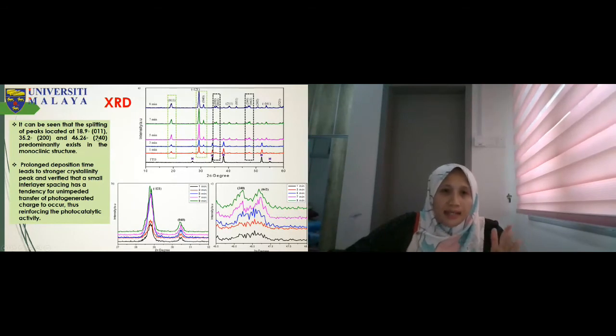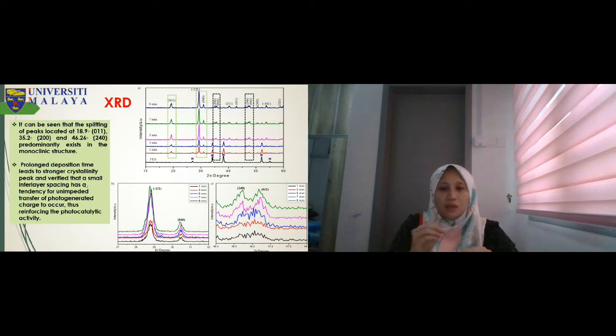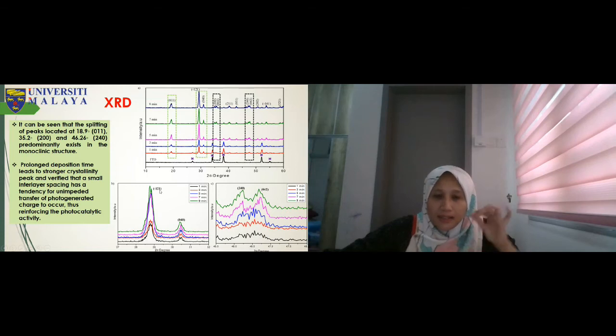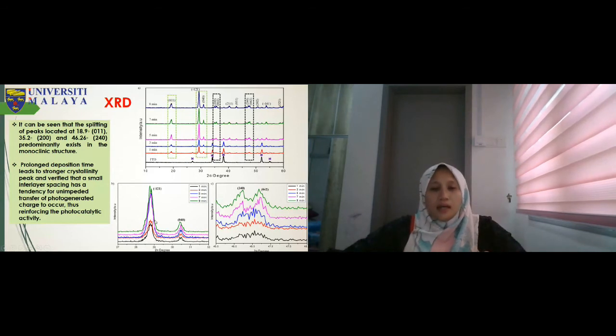So it can be seen that the splitting of the peak located at 19.9 degrees, with HKL numbers 200 and 240, predominantly exists in the monoclinic structure. And then after we prolong the deposition time, it leads to a stronger crystallinity peak and verifies that a small interlayer spacing has a tendency for unimpeded transfer of photogenerated charge to occur, which will enhance the photocatalytic activity. So this one is for the 1 1 HKL number. I make it larger so we can observe that after we increase the deposition time, the size increases, so it becomes more crystalline for the BiVO4 photoanode.